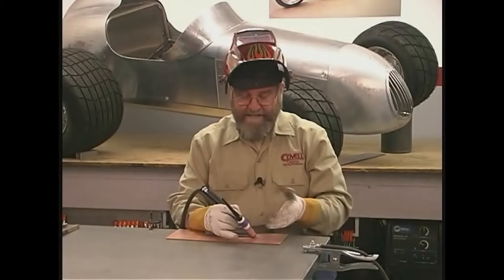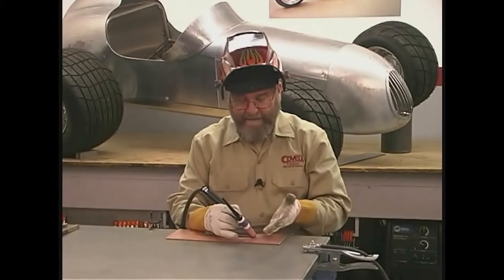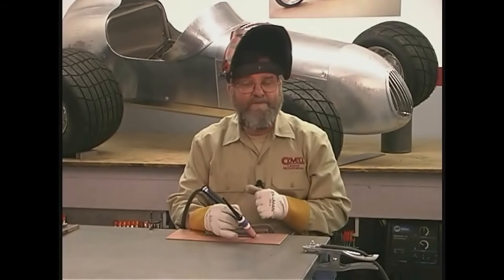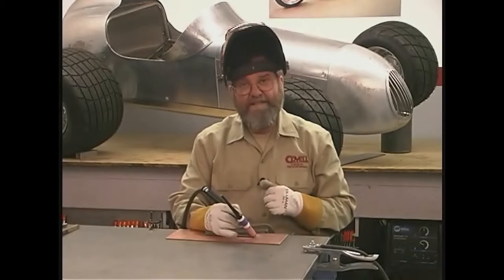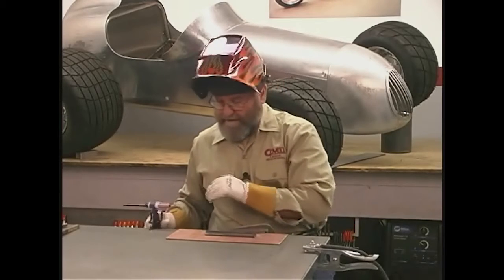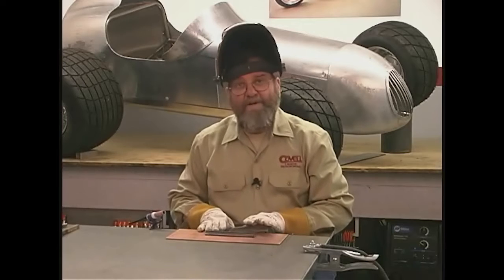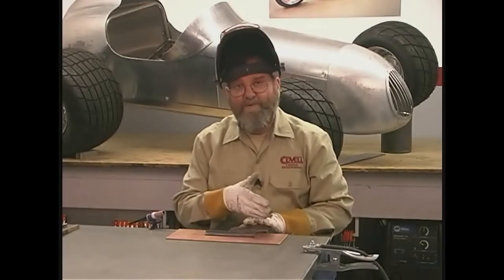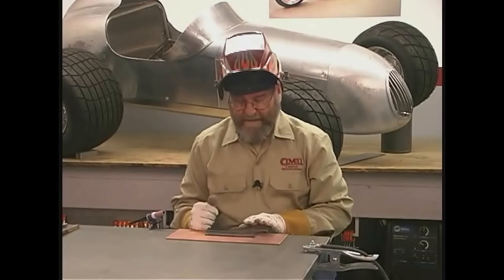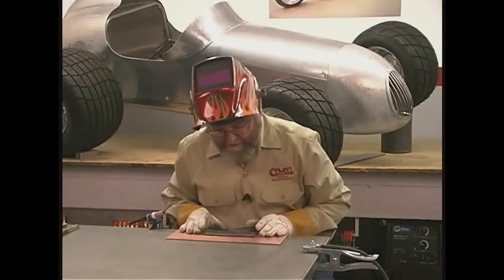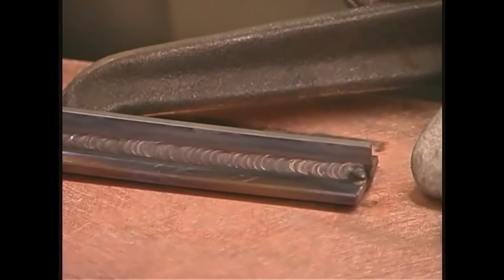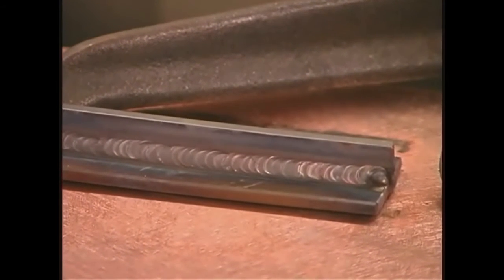Okay, and as always, I'll keep the torch in place, flooding the base metal and the tungsten electrode with shielding gas to prevent them from oxidizing. I forgot to mention that the alloy I'm welding is 304 stainless, which is far and away the most common alloy. That's why I chose the 308 filler rod. But let's take a close look at the weld itself. Stainless welds beautifully. It flows like water. And typically a weld made on stainless will have a finer and more uniform bead pattern than any other material.